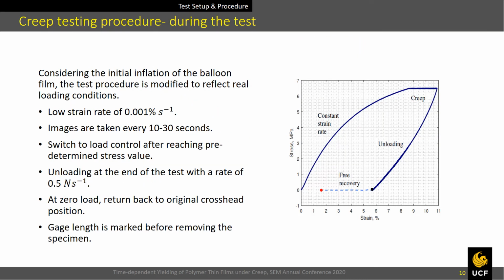Considering the initial inflation of the balloon, the test procedure is modified to reflect real loading conditions. A typical test procedure can be seen in the figure. The test comprises 3 steps: constant strain rate loading, creep loading, and unloading. Strain rate of 0.001% is specified until preset stress value is reached. Once creep stress is reached, it is maintained for a duration of time. Then, the specimen is unloaded at a rate of 0.5 Newton per second, and at zero load, crosshead is moved